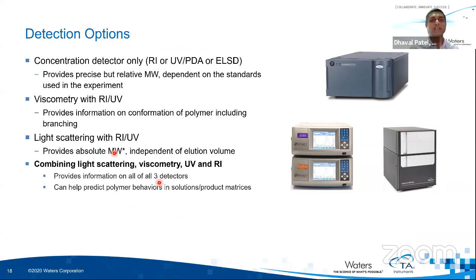A very quick slide on the detector, as I mentioned. Over the years, we also have advances in detectors. One of the common detectors that was used is the RI or refractive index detector, which gives you a precise measurement of molecular weight distribution, but is not an absolute technique. But most of the time, the polymer chemists want to look at the distribution. Then we have viscometry, which typically gives you structural information such as branching in your polymer. Then we now have companies who offer what we call triple detection, a combination of light scattering, viscometry, and UV and RI detectors, all in one. So this can help you predict polymer behavior as well as structural information in a single analysis.